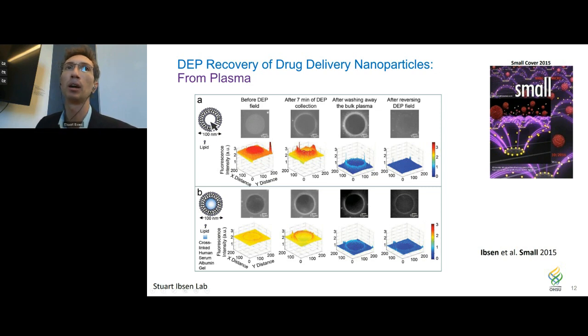which was really exciting because these particles mimic in a lot of ways the extracellular vesicles that are released by tumors. What we see in these pictures is the overall fluorescence level before dielectrophoresis is added. After 7 minutes of collection, we see really good accumulation of particles around the electrode edge. They're held there through a wash to purify them, and then we can recover them off the chip for off-chip analysis if necessary. So this got us thinking, could we use this technique to recover exosomes and other kinds of nanoparticles from plasma?